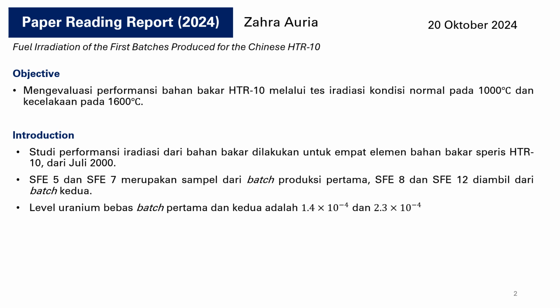The study of fuel performance by irradiation is carried out for four HTR-10 spherical fuel elements, and it was started in July 2000. The sample fuel elements 5 and 7 are both from the first production batch. Meanwhile, the sample fuel elements 8 and 12 are taken from the second batch. The free uranium levels of the first batch and the second one are respectively 1.4 times 10 to the minus 4 and 2.3 times 10 to the minus 4.